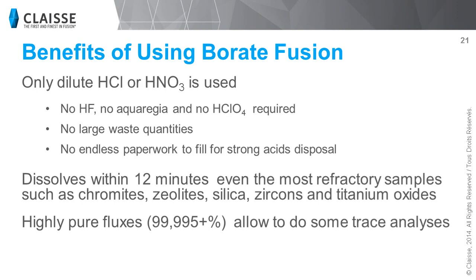One of the great advantages of using borate fusion and peroxide fusion is that you don't have to use strong acids such as perchloric, nitric, or hydrofluoric acid. There is no need to heat strong acids for a long period of time in your lab. With borate fusion, you can dissolve any samples within a few minutes using diluted acids. The borate fusion method is very simple. You only need a borate flux, sample, and if needed, an oxidizer.